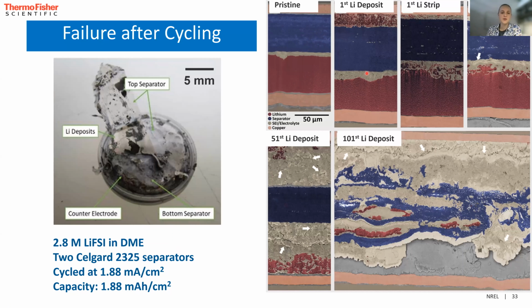With the first lithium deposit, you can see the lithium shows up fairly porous and intermixed with some electrolyte and SEI. Then as you strip that away, some of the lithium was left over, and the lithium that redeposited on your counter electrode was very open and porous. Cycling 10 more times, you can see that there's actually a lot of SEI that has built up and SEI that has infiltrated into the separator with time.